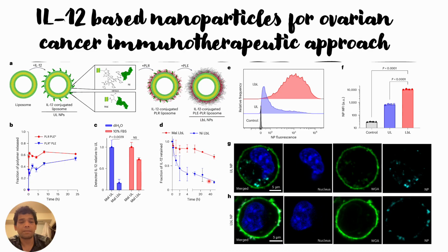In the case of 10% FBS, they found that the IL-12 removal for the uncoated nanoparticles is high, whereas the IL-12 removal for the coated nanoparticles, that is their optimized nanoparticles, is lower, indicating that it will have a higher lifetime within the patient.